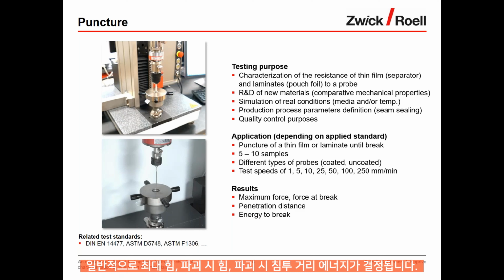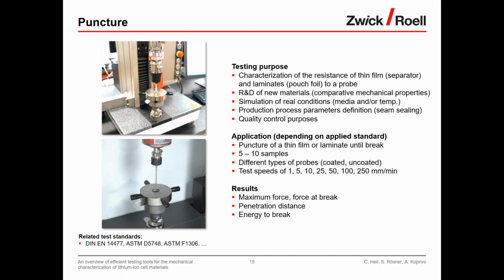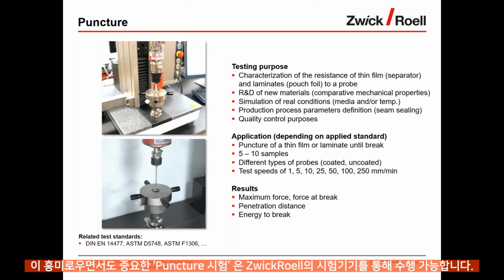Typically, the maximum force at break, penetration distance, and energy to break are determined. This is a fairly standardized test. It's derived from the plastics industry and can be fairly well adapted to the requirements of battery materials testing. I've listed on the left side a couple of standards which can be referenced. They apply not to battery cell tests, but to other related tests for the plastics industry, paper industry, metals industry, and so on. So it's a cross-reference to other standards in the industry. So the puncture test is important and interesting, and can be done with our universal testing machine.